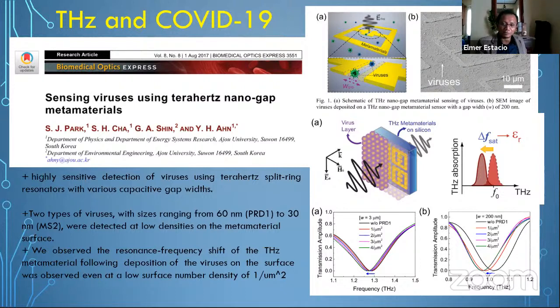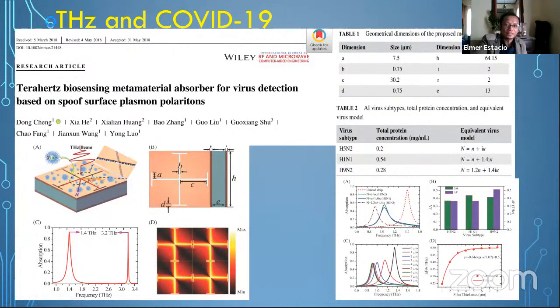They were able to show using a metamaterial, what they call a nanogap metamaterial, very, very sensitive detection of a virus having dimensions of around 60 to 30 nanometers, even with just a very low particle density of one particle per square micron surface density. Because when you drop the solution, it becomes practically a surface, not a volume. So that's one promising thing that I'm looking at. And this is more of a simulation work.